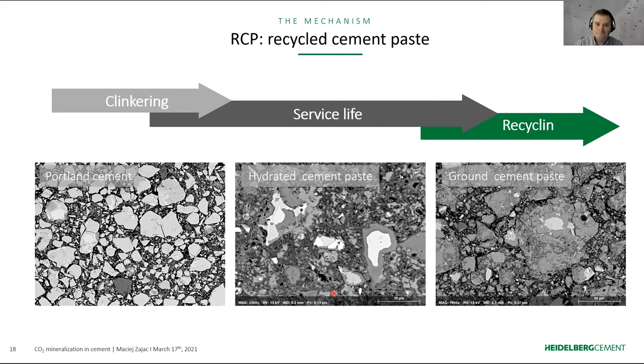Yes, okay. So to answer the first part of the question, as shown on this additional slide that I have, we use the synthetic materials because at the very beginning we wanted to check if the process works at all. So we took a Portland cement, made a hydrated paste over several months of hydration, and then just dried the paste and ground it. And then made all the carbonation and performance testing later on in concrete.